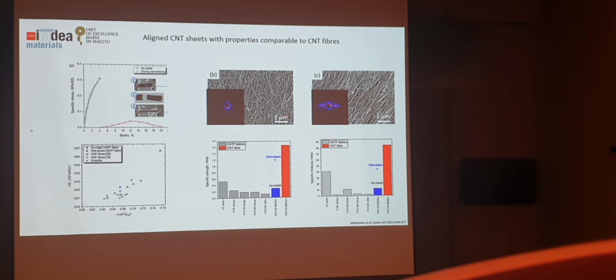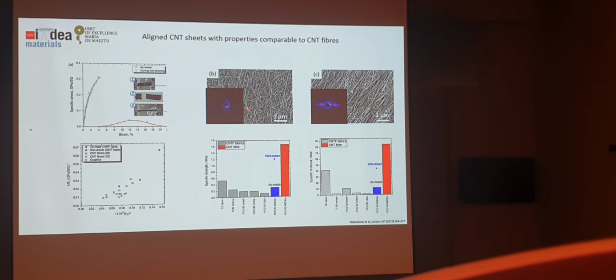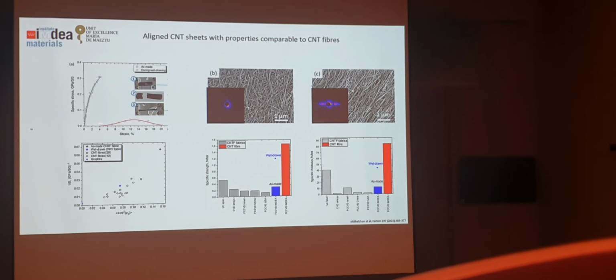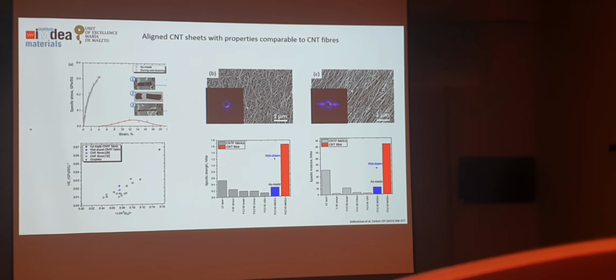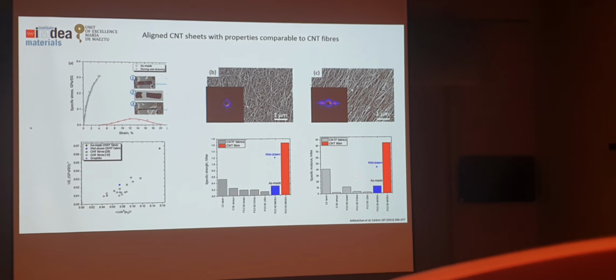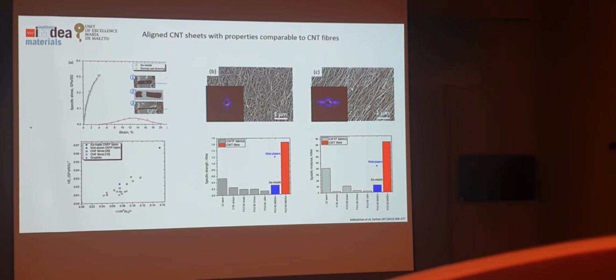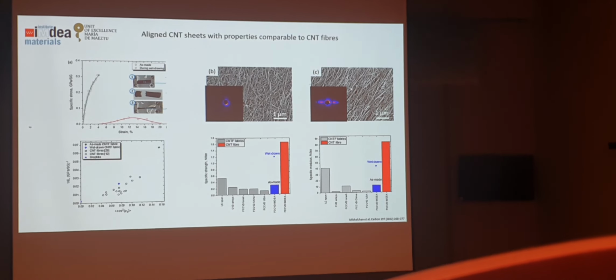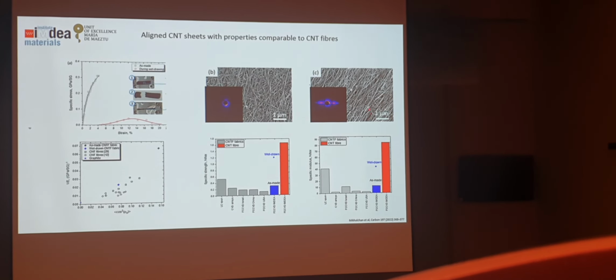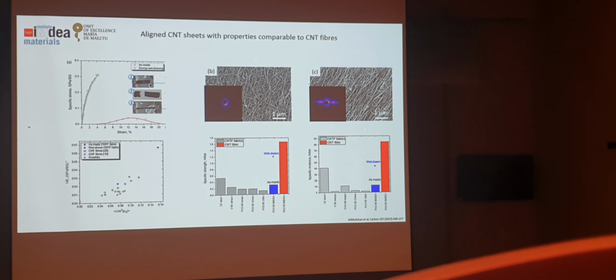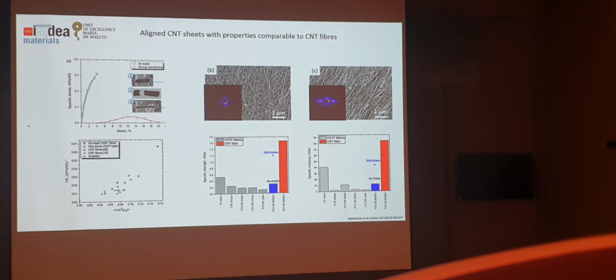So we could do some alignment by control of the drawing process of the aerogel or through wet processing. This is an example of wet drawing, and you can see that with little force you can draw these materials. That's good because it means you can get decent properties in sheets. This is about 1.2 Newton per tex in a wet drawn material, and this is 50 Newton per tex modulus in wet drawing. That's also particularly interesting for me because I think if you can align sheets, you have an aligned fabric. You actually never have to make a fiber in the first place.